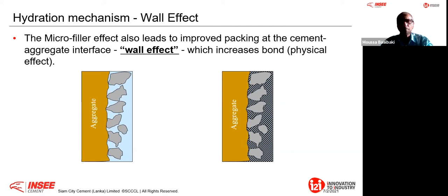Therefore, if you go to high performance concrete, to better quality concrete, you need to develop this wall effect, you need to increase the bond. How you increase the bond is to take out the Portlandite, or the calcium hydroxide, and turn it into what we call calcium silicate hydrate. That is really important. That is why we have what we call the physical effect, where you can highly improve the compressive strength by having this kind of reaction.